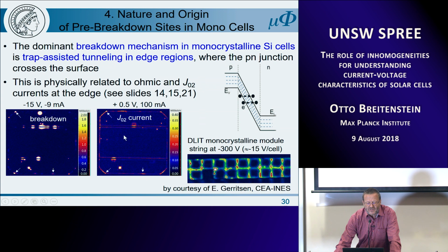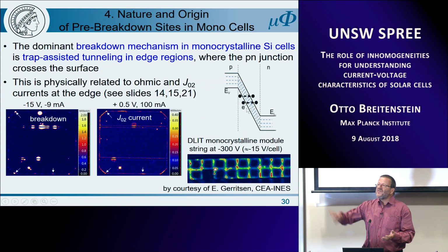This is the J02 current. And this is the breakdown current at minus 15 volts. And we see here where we have the local maxima of the J02 current, we also have the local maxima of the breakdown. So we believe the mechanism is basically the same as the ohmic current, which we also have found by these extended defects there, with the exception that it is now field dependent.